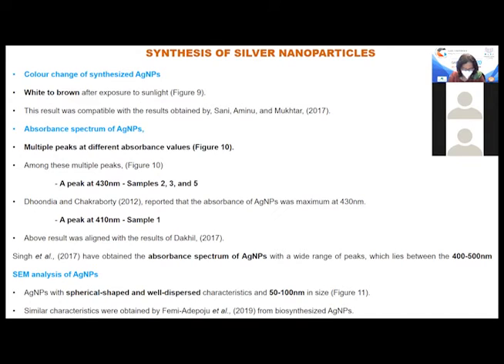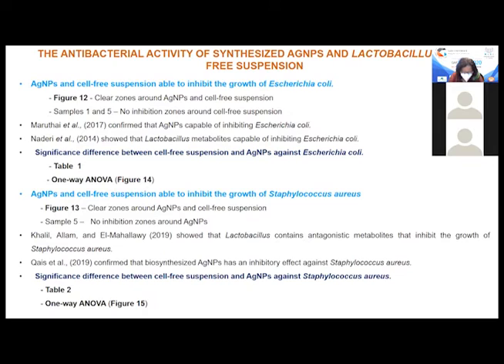Further confirmation was done by the SEM analysis. We observed spherical shaped, well dispersed silver nanoparticles, and similar characteristics were obtained by Femi 2019 from biosynthesized silver nanoparticles. When we come to the antibacterial activity, the cell-free suspension contains metabolites produced by Lactobacillus, and some of these metabolites are responsible for the antibacterial effect.